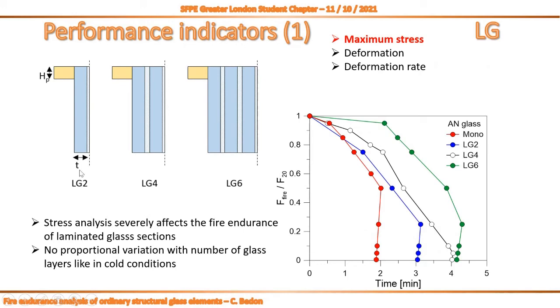So let's try to do again the same study, at least for stress analysis, in terms of laminated glass sections. As you can see, the red curve is the monolithic one with identical size. The blue one is a double laminated section with 2 glass layers. We have then the laminated section with 4 glass layers, and finally the section with 6 glass layers. Why the reason of this comparison?